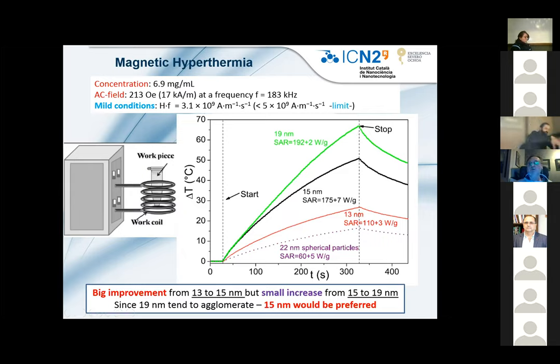So similar to the NMR results, 15 nanometers would be preferable for biomedical applications because the properties are rather good and they do not agglomerate. And if we compare the SAR values with commercial spherical particles, these are much smaller, less than half of the ones we obtain with the cubic nanoparticles.